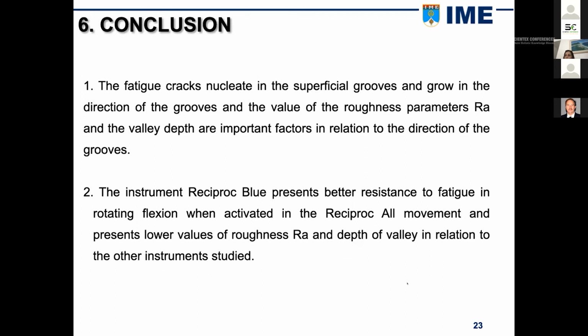Conclusions. The fatigue cracks nucleated in the superficial grooves and grow in the direction of the grooves, and the values of the roughness parameters, RA and valley depth, are important factors in relation to the direction of the grooves. The instrument Reciproc Blue presents better resistance to fatigue in rotating bending when activated in the Reciproc All movement, and presents lower values of roughness, Ra, and valley depth in relation to the other instruments studied.